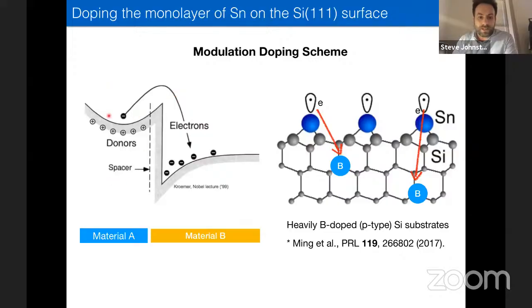So the idea is to take some heavily doped system, sandwich it together with some clean system, and let the mismatch in the chemical potentials transfer charge out of the doped system into your clean system. So in this monolayer system, the way this is done is essentially you take really heavily doped boron silicon substrates and then grow the monolayer on top of that substrate. And so the idea is that boron wants to pull electrons out of the tin monolayer, and that leaves behind a hole doped monolayer. And because it's a modulation hole doping scheme, it can do this in a very clean way without introducing a lot of defects into the tin layer. So this is very different from the way you dope conventional oxides, for example, like cuprates.